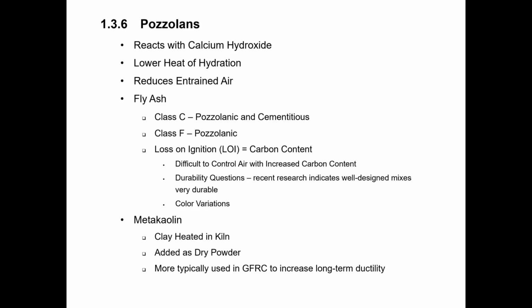So the most common pozzolan that we see in use at precast plants is fly ash. Fly ash comes as a couple of different classes, Class C and Class F. The main difference between these two is that Class C fly ash does have some cementitious properties, not very many. It's not very cementitious, but it does have some cementitious reactivity that's available, whereas a Class F does not. So both of these react well with calcium hydroxide, but Class C does have some basic cementitious properties, and the Class F does not.